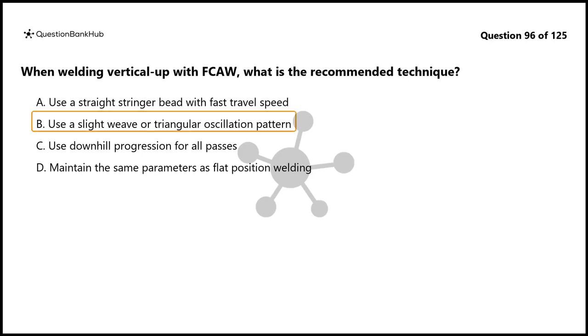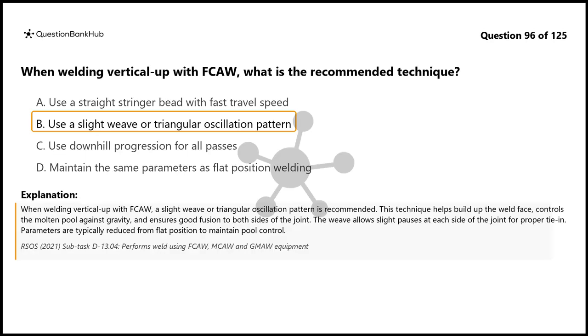Use a slight weave or triangular oscillation pattern. When welding vertical up with FCAW, a slight weave or triangular oscillation pattern is recommended. This technique helps build up the weld face, controls the molten pool against gravity, and ensures good fusion to both sides of the joint. The weave allows slight pauses at each side of the joint for proper tie-in. Parameters are typically reduced from flat position to maintain pool control.